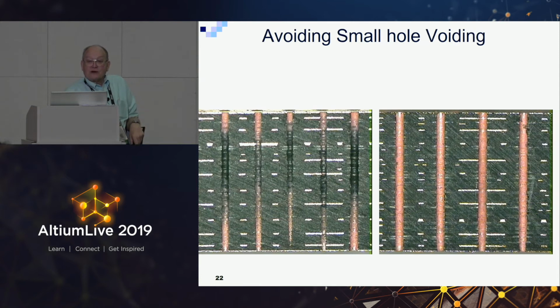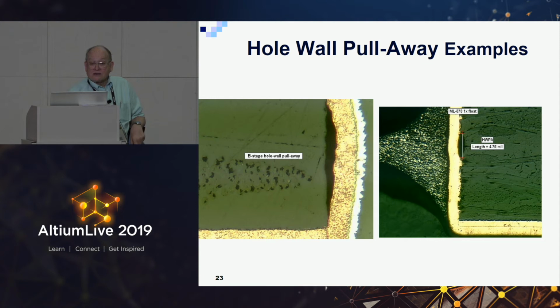And avoiding this small hole voiding where you have big thick boards and very small holes, which is why I advocate HDI. You can learn how to design the backplane multilayer with half the number of layers of the conventional multilayer, which minimizes the hole aspect ratio and that whole problem to begin with. And there's a thing called hole wall pull-away. Well, the metallization pulls away from the dielectric